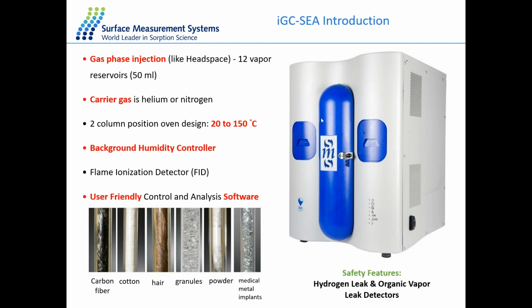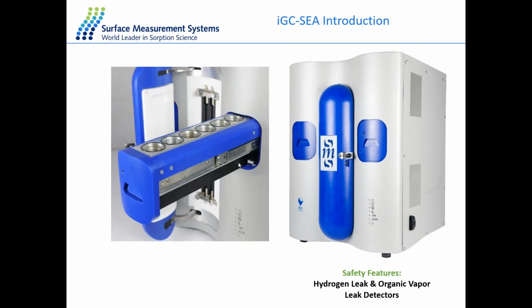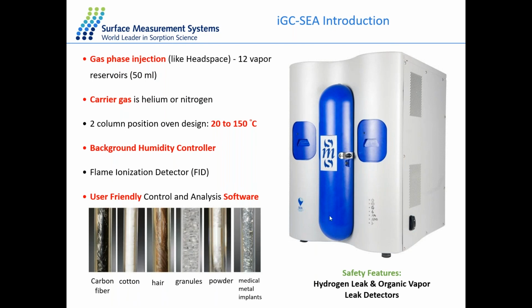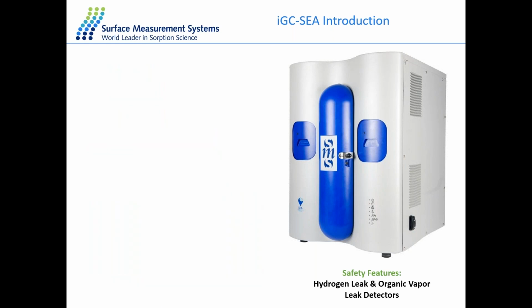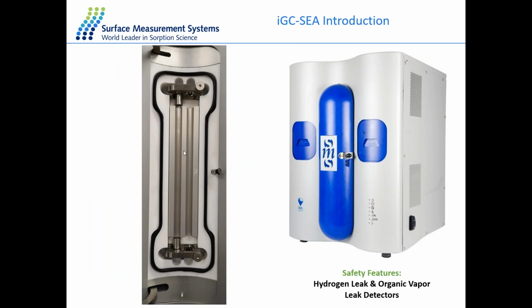So this is what a typical iGC-SEA system looks like. It has 2 drawers on either side and a door in the middle. When you open up each drawer, we can accommodate 6 different reservoirs. This is where your solvents would go in. To measure surface energy, we need a mixture of some alkane non-polar probes and some polar probes. The system has a carrier gas of either helium or nitrogen. When you open the door in the middle, what you would see is two column positions. So here's 1 and 2, and this is where you'd put your sample.